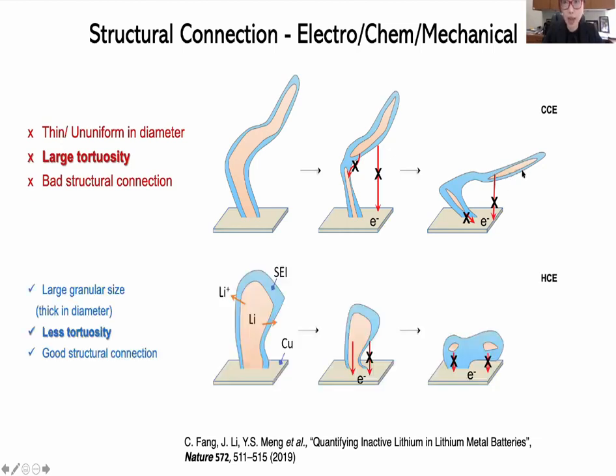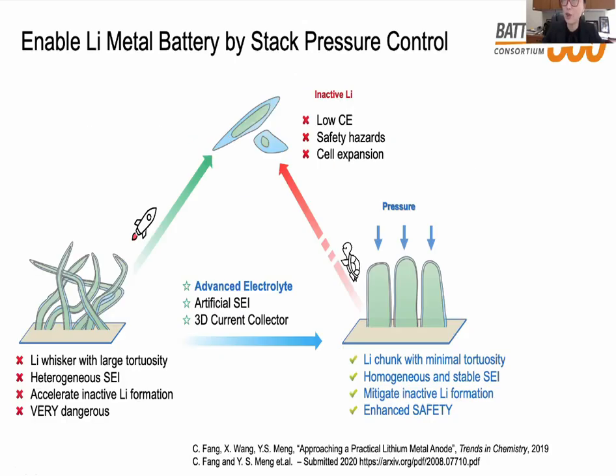But if you have large granular crystals, you actually run less into such a problem, right? So naturally, because of this microstructure phenomena, we think, okay, what's the best way to ensure that the contact is very good? So that actually led us to propose three things. One is, of course, you need the electrolyte where the nucleation site always nucleates large grains instead of these kind of tortuous whiskers type of lithium.